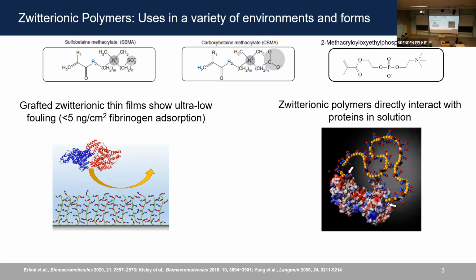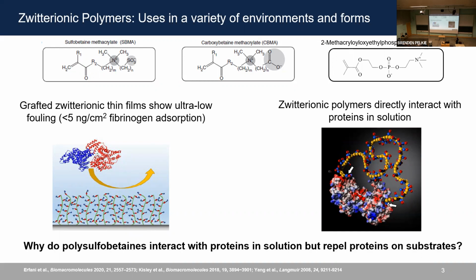In a recent study, it has been shown that Zwitterionic polymers do interact with proteins in solution. It was shown that the positive and negatively charged ions and their spacing, shown here as red and blue balls along the yellow polymer backbone, are very important in interacting with the charged patches on the surface of the protein. So the question that I wanted to address is, why do polysulfobetaines, as model Zwitterionic polymers, interact with proteins in solution, but show really good repelling properties when grafted on a substrate?